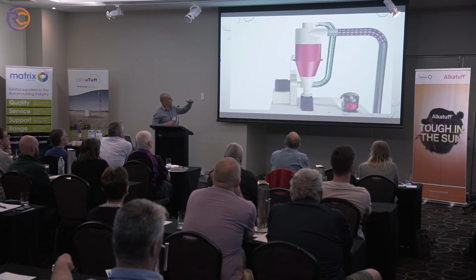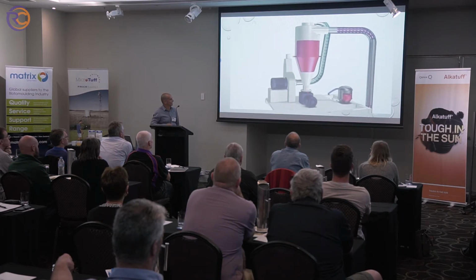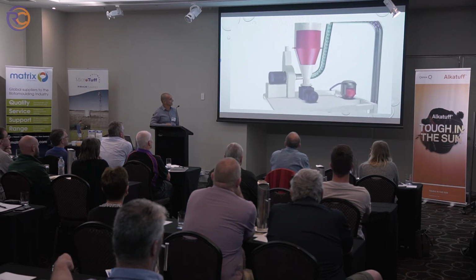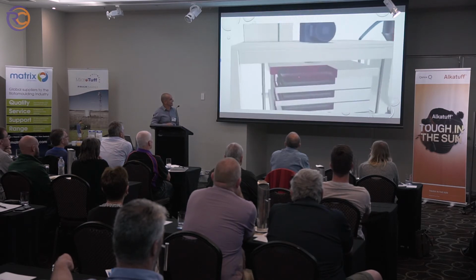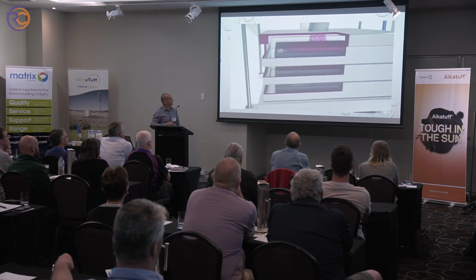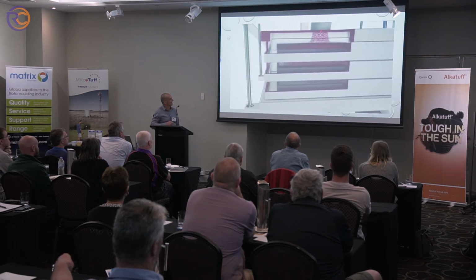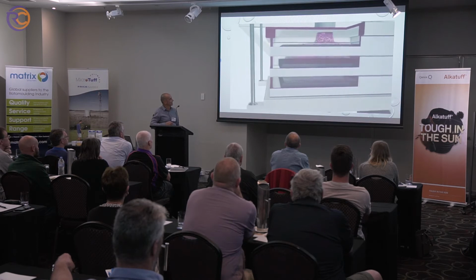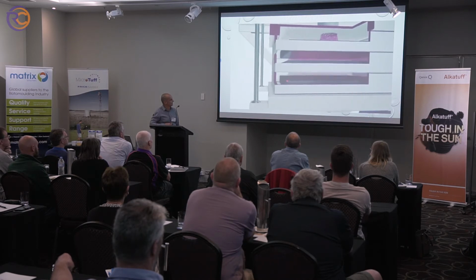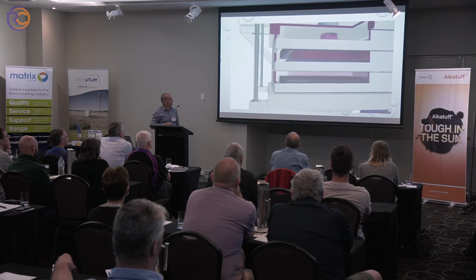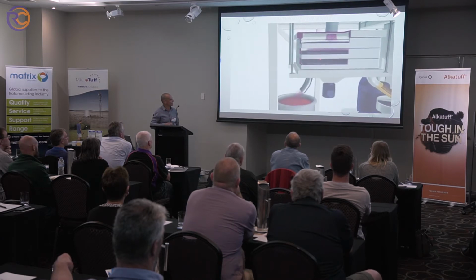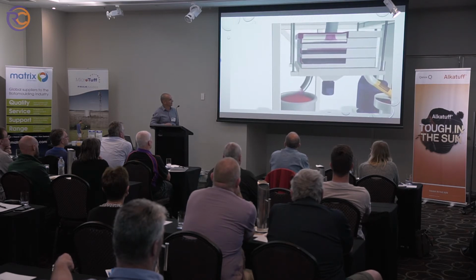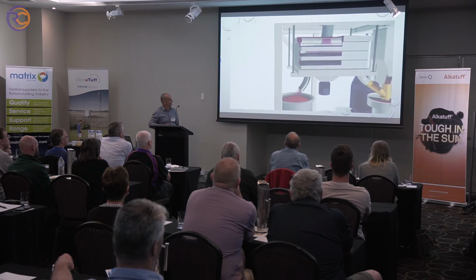The powder drops down into the rotary gate, which is sealed, so that no air can pass through and suck the powder back up through the screening system. And then you've got the powder, and it's going round through the different screens until it either goes through the screens into bagging, or it goes back out to be reground.